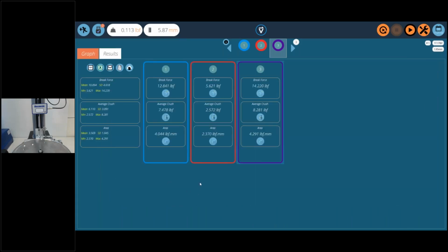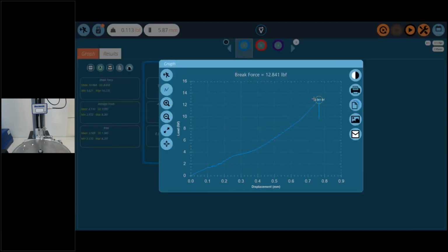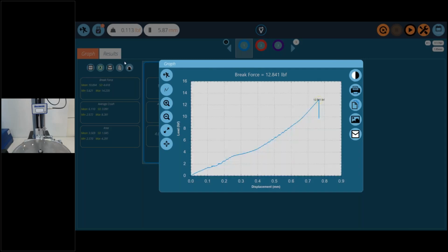Once the test samples are completed, you can go over to the test results tab, which will essentially tell you pretty much everything you've asked for as far as calculation. So the break force, it's catching that at about 12.8 pounds. That's where we're seeing the break force for test sample 1.